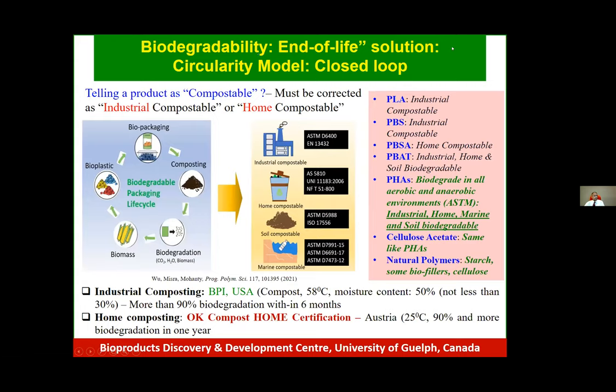For biodegradability, you must talk about the end of life solution, circularity model, and closed loop. So these are a few examples of various biodegradable polymers. I showed this graph already. This is a complete recycling in a composting environment. Nowadays, people talk about various composting: industrial compostable, home compostable, soil compostable, marine compostable, with various standards. One polymer, let's say PLA, polylactic acid, is industrial compostable. That means it is degraded 90% and above in composting conditions in 180 days. Polybutylene succinate is industrial compostable. PBSA is home compostable. Home compostable means the home composting standard is different. The temperature is a little lower. Here we use a temperature of 58 degrees C and moisture content around 50%, but for home composting we use 25 to 30 degrees C.